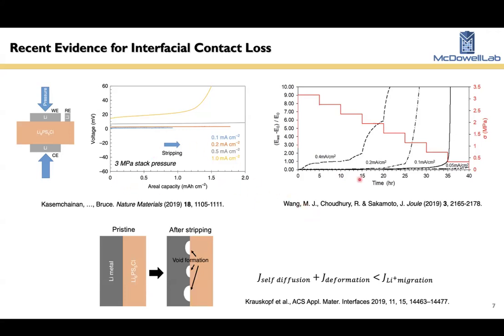So Peter Bruce's group, Jeff Sakamoto's group, and Jürgen Janek's group all came out with papers around the same time that basically showed electrochemical evidence for the fact that you can lose contact at a lithium solid electrolyte interface during stripping. And fundamentally, this is a fairly simple process, I guess, intuitively, but in reality, it could be much more complicated.